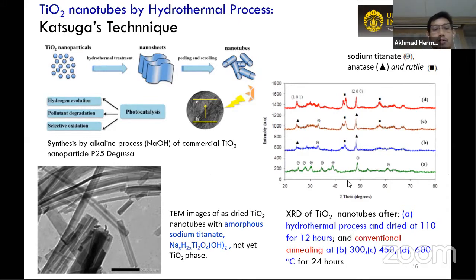Of course, the TiO2 nanotube can also be synthesized by using an anodization process or some other physical process. This TiO2 nanotube is very useful for the dye-sensitized solar cell and also for hydrogen evolution, pollutant degradation, and selective oxidations. But something that we have to remember is that the result of the hydrothermal process of TiO2 nanoparticles immersed in sodium hydroxide alkaline solution is that the nanotube is still in the form of amorphous sodium titanate. Because it was mixed and immersed in sodium hydroxide, a very strong alkaline solution, the resulting nanotube is still in the form of amorphous sodium titanate. There is still the element of sodium in the nanotube, so it is not purely a titanium oxide nanotube yet.